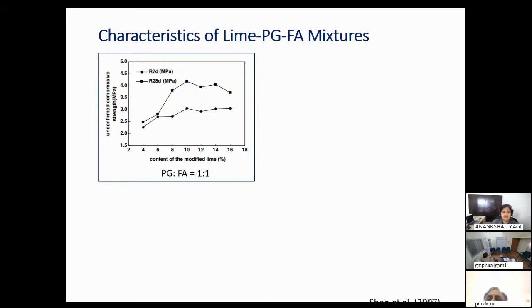So basically, the characteristics of lime, phosphogypsum, and fly ash mixtures were studied. In this one, it was seen that phosphogypsum and fly ash were added at 50% with modified lime. In this research, they say the modified lime used lime and some kind of additive, and I think mostly it should be the alkali activator, which is generally used for fly ash. They didn't mention it, but they said it is a modified lime, that is, quicklime with some kind of additive. So they found that with the addition of lime, the strength increased up to 10% of lime.